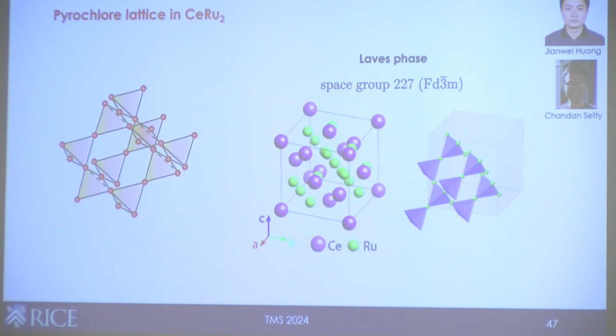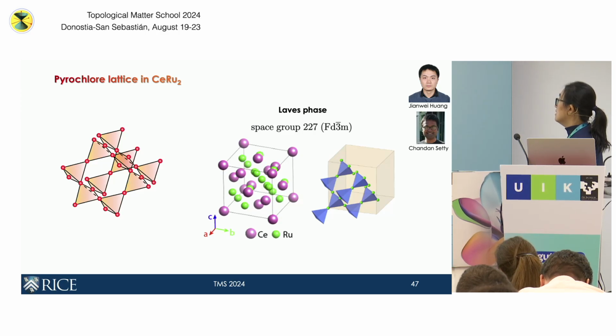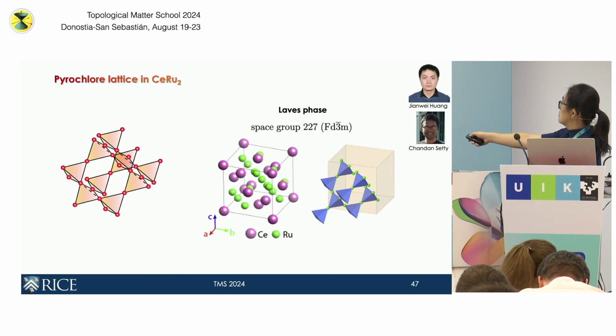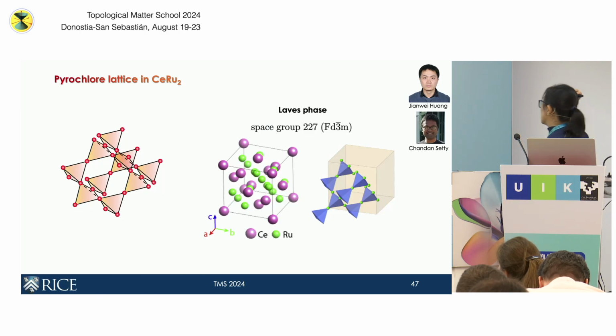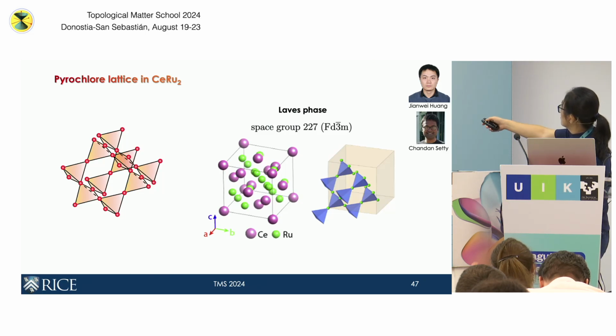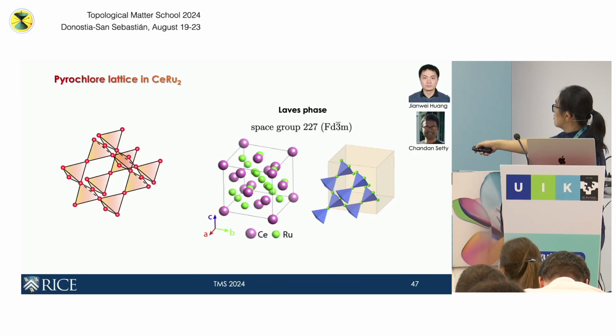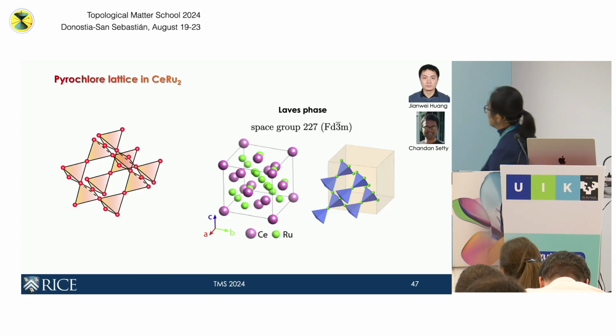Okay, all right, so how do we see this in real materials? We just happened upon a material. One of the first that we happened upon is this compound cerium ruthenium-2, which belongs to this Laves phase that Stephen also talked about. I just want to give credit to Chandan Setty, a theory postdoc working with Timel's group, who is starting his own position at Iowa State very soon. He was the first one that told us about this pyrochlore lattice and recognized that this material, even though it has a certain direction that looks like a Kagome, is really dominated by pyrochlore physics instead of Kagome. And then Jianwei is our postdoc who really did the experimental aspect of this.